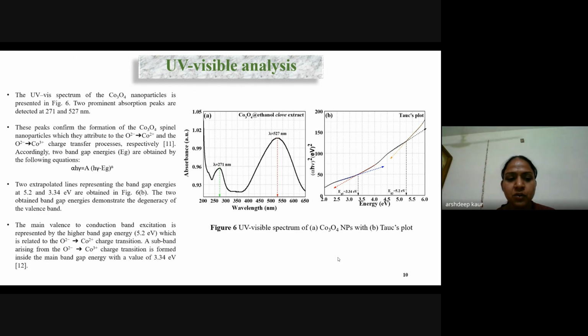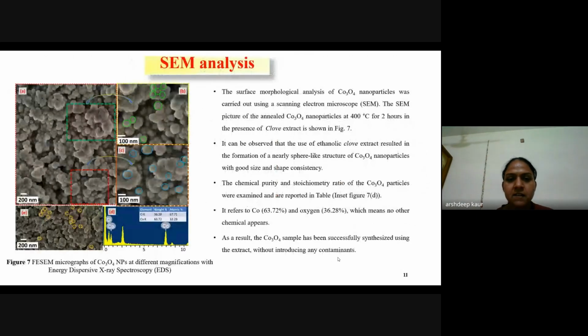And this shows the two band gap energies at 5.2 and 3.34 electron volts. The two obtained band gap energies demonstrate the degeneracy of the valence band. This is the SEM analysis of the prepared particles. The SEM analysis shows the nearly sphere-like structure of Co3O4 nanoparticles with good size and shape consistency.